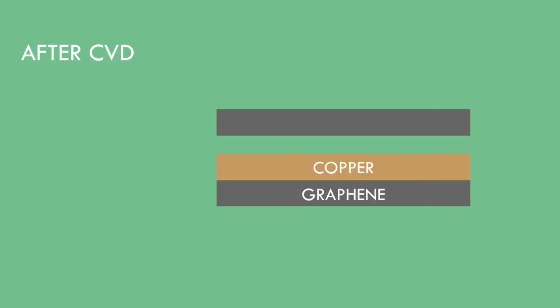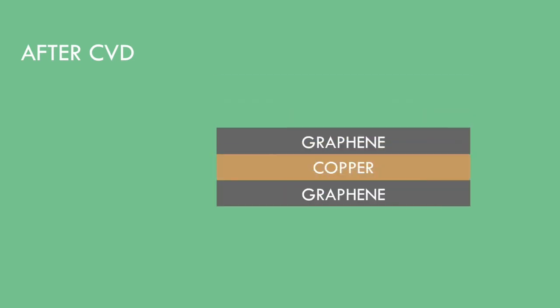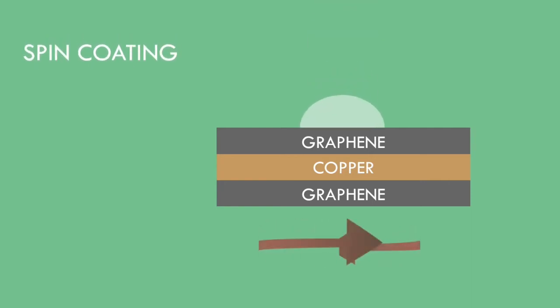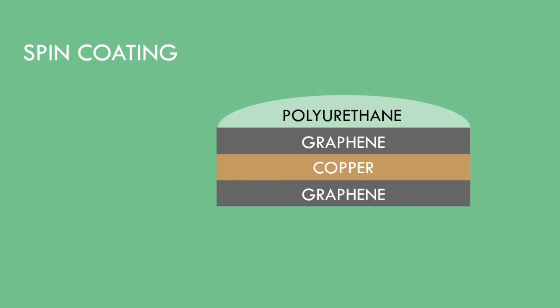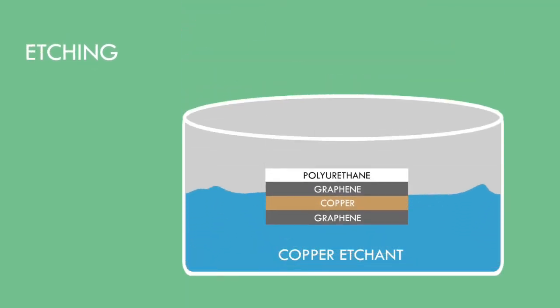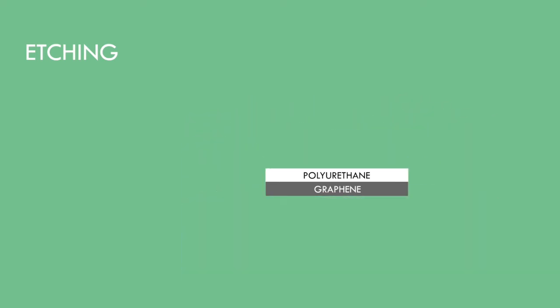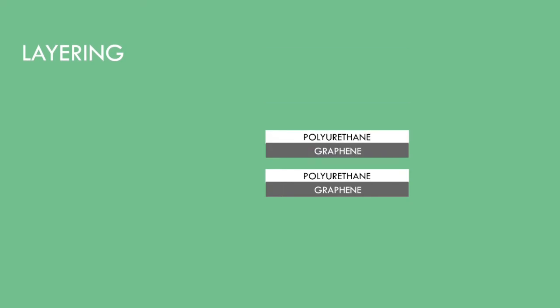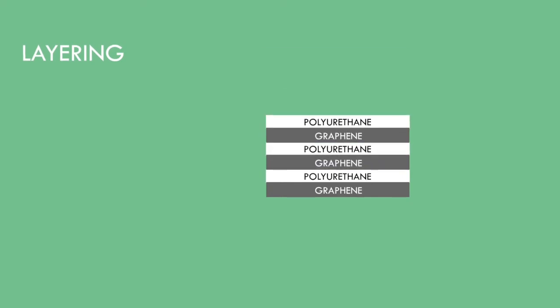Using chemical vapor deposition, graphene is grown onto copper foil. A polymeric support layer is then spin-coated on top of the module. This support layer is allowed to cure in preparation for the etching process. Using APS 100 as the copper etchant, the underlying graphene layer and copper foil are removed. Using polyurethane as the adhesive layer, the remaining modules are stacked together to create a laminated composite.